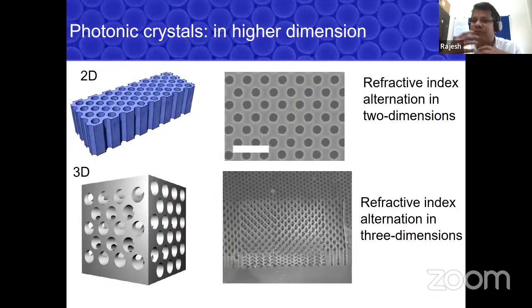So what I introduced is a band gap for photons and how we understand that, using a one-dimensional system. But we can also have this periodicity in dielectric constants in two dimensions and three dimensions. So this is basically a two-dimensional photonic crystal where you take a sample, for example a silicon wafer or something. You have a drilling machine. Now you make holes. You make periodic holes. And for periodicity, we are talking of 300 nanometers, and the diameter is also of the order of hundreds of nanometers. So it's as simple as that.